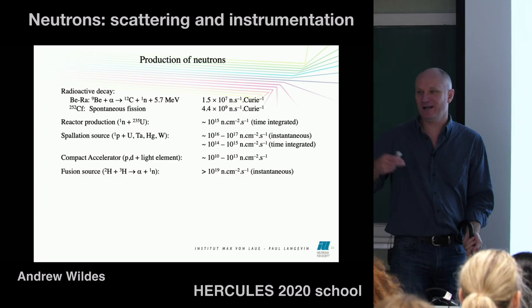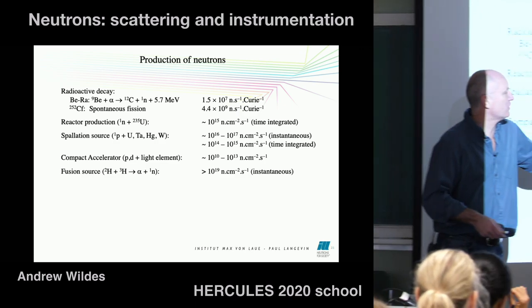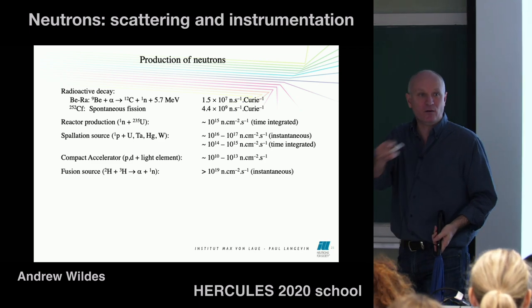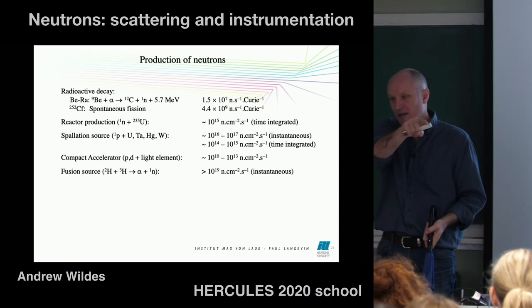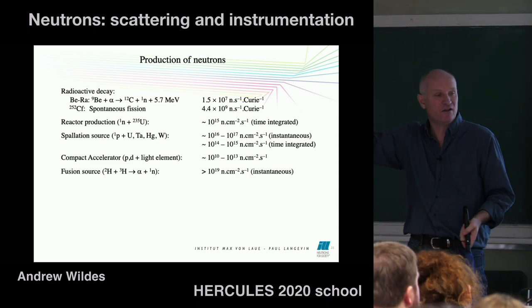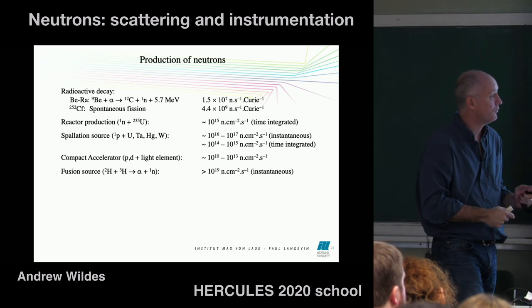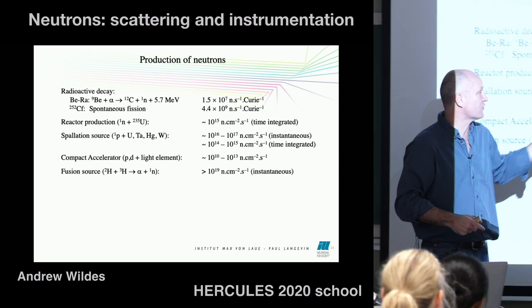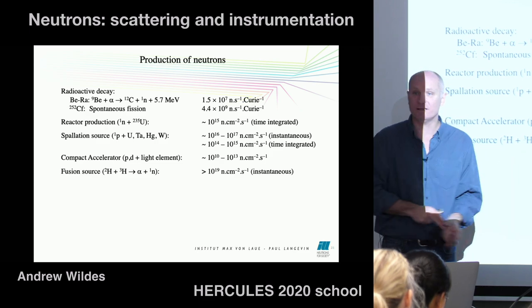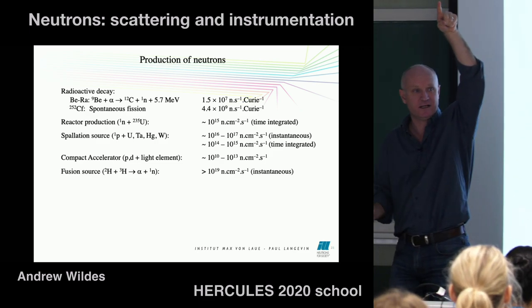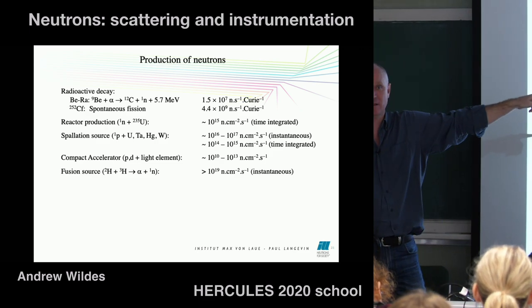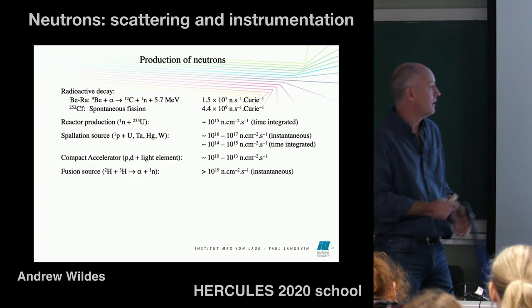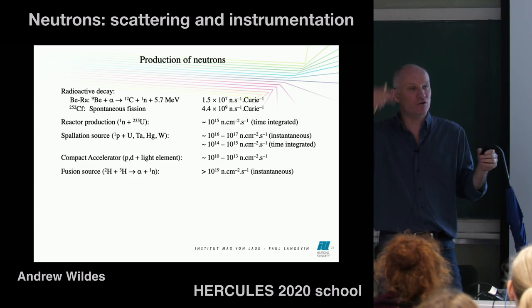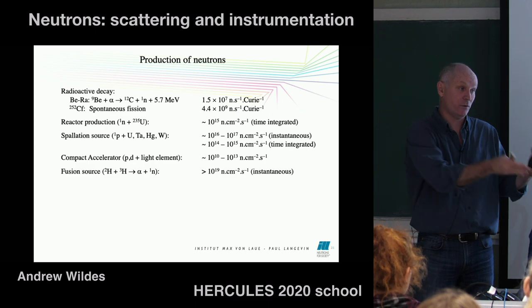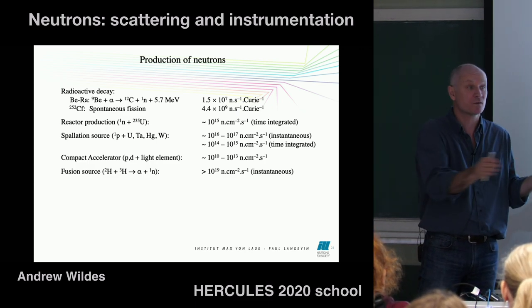Spallation sources, depending on who you talk to, tend to be pulsed, so you'll get a spike in the neutron production and then you'll get nothing. And then you get another spike and then you get nothing. So there are two numbers that are important. One is the instantaneous flux. And here you'll certainly get a lot more neutrons in your instantaneous pulse than you will out of the reactor. On the other hand, if you integrate over time, you get correspondingly a lot less, because for a lot of that time, your source is off.